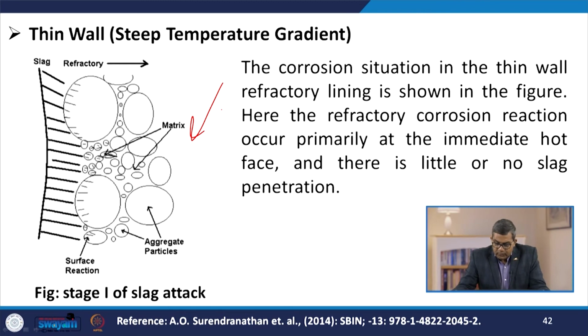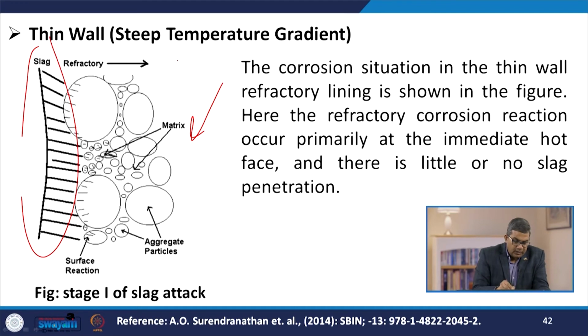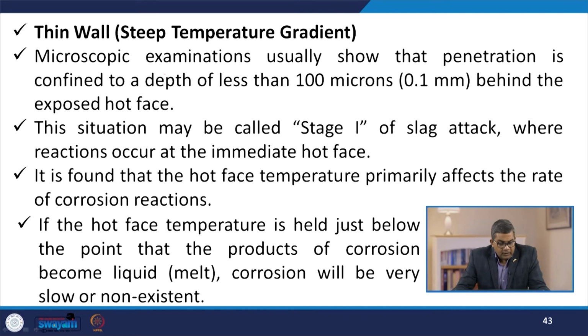Now, here the refractory corrosion reaction occurs primarily at the immediate hot face, and there is little or no slag penetration. Here you see the slag zone in this particular figure. Microscopic examination usually shows that the penetration is confined to a depth of less than 100 microns, or 0.1 mm, behind the exposed hot surface. This situation may be called stage 1 of slag attack, where the reaction occurs at the immediate